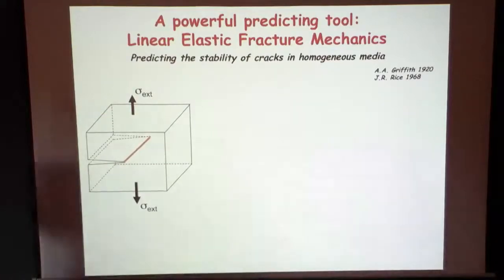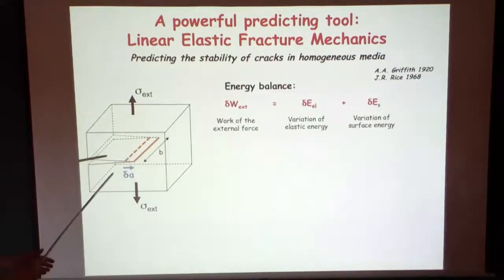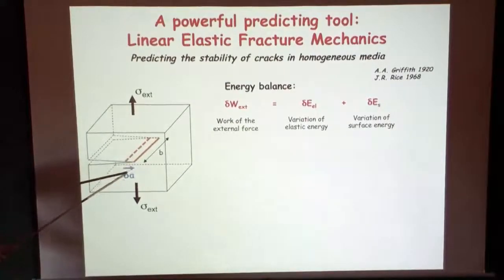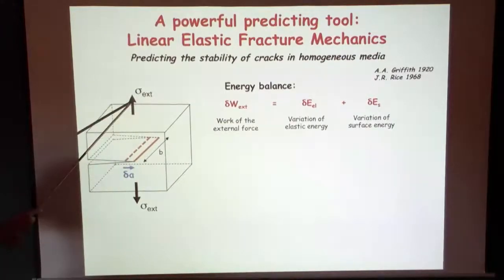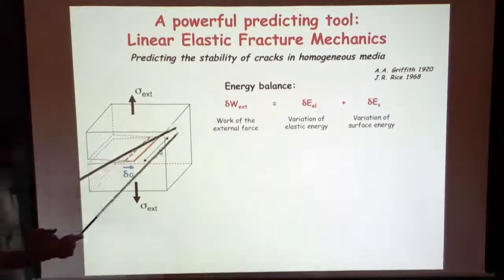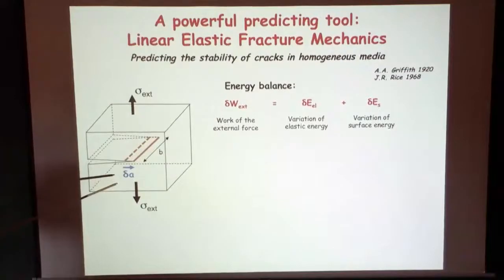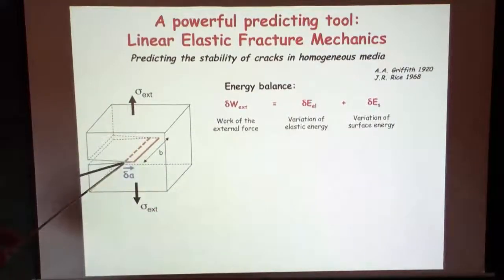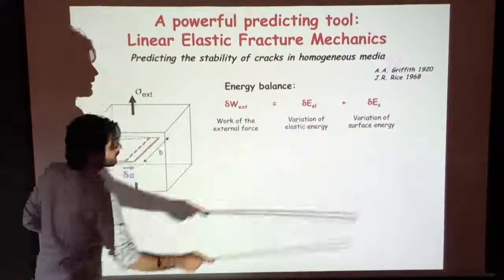Actually, a powerful way to look at the problem is to consider energy transfer, energy balance. When you have a crack in your system that is going to move over some incremental length delta A, then instead of looking at the stress field, I'm going to look at energy variation. During this propagation, the work of the external force is going to balance the variation of elastic energy in the solid, which is under some stress, and a variation in surface energy, or if you want, an increase in dissipation, because you propagate a crack, or you create new surfaces. This costs you some energy, which I note delta ES.